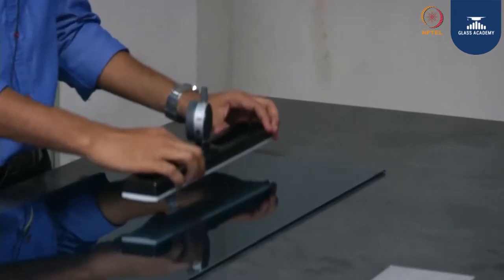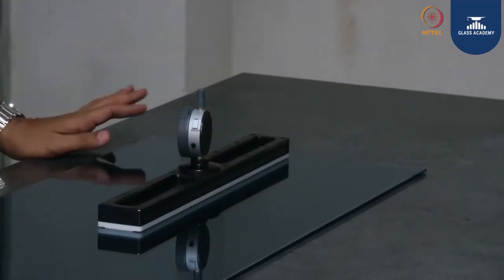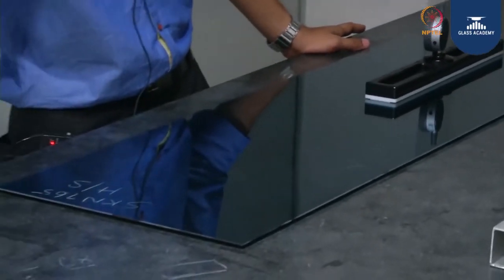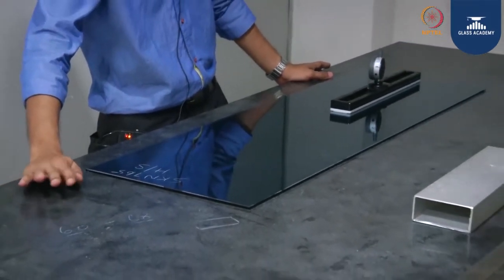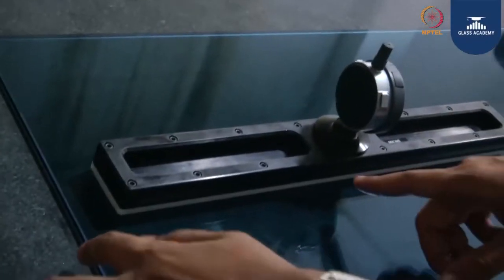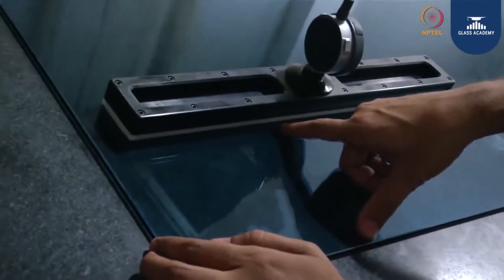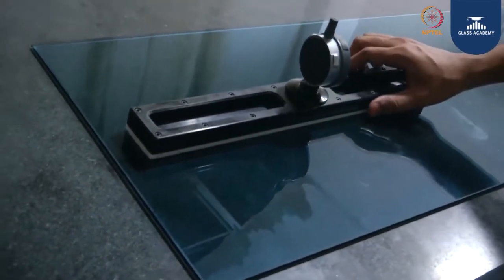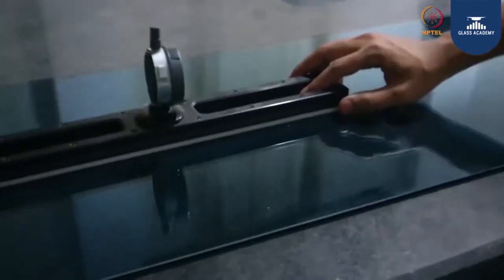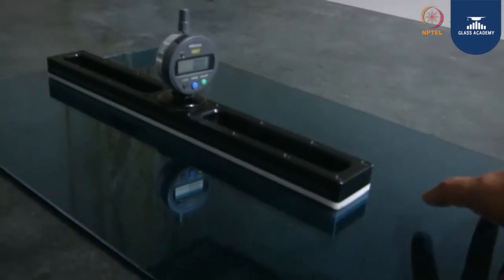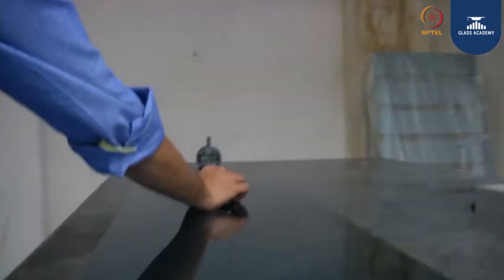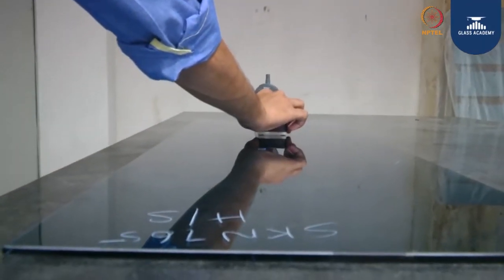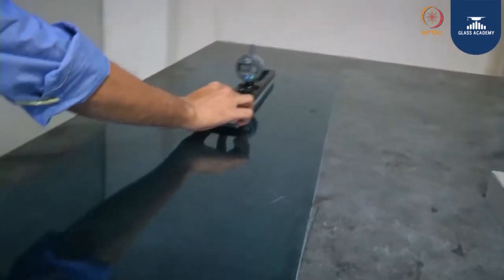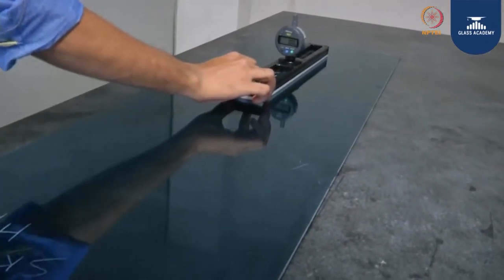First we need to place the roller wave gauge on the glass. We need to ensure the flatness of the table, and we need to make sure that glass is resting flatly on the surface. First we need to leave 150 mm for edge lift. Next we will be starting the gauge, the movement of the roller wave to be perpendicular to the glass direction. Now we need to keep the roller wave gauge on the glass surface, and we need to drag it on the glass surface to note down the reading.